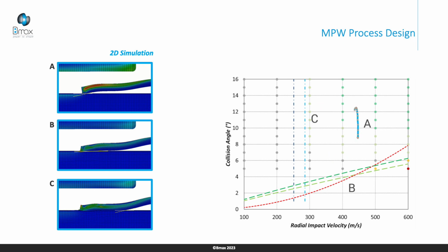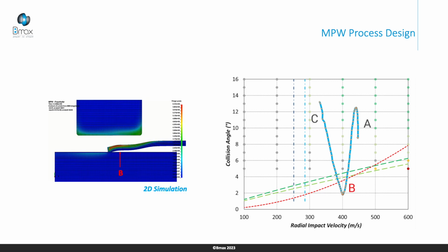So as you can see, at point A, we have a very high angle and a good speed. We are in the middle of the welding window. After, during the process, we have a flat impact. So for a good velocity, the angle decreases and re-increases after. At point B, we are out of the welding window, and at C, we have a large angle at the end of the process, and we are again in the welding window. So according to this analysis, we can say we maybe have an issue at point B.